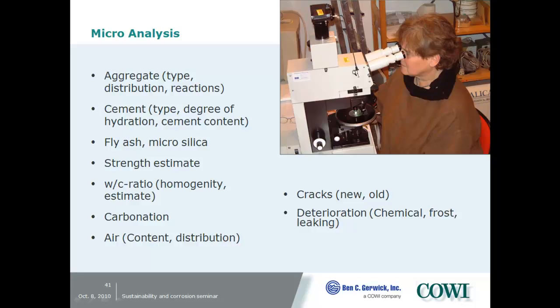Strength estimate, as said. Water cement ratio we can also estimate to a fairly good accuracy. You need to have some references, and what you evaluate is the porosity. If you have a very light green color on your cement paste, that's a high water cement ratio, and vice versa. So you need references to do so. Trained petrographers can evaluate with an accuracy between 0.02 and 0.05 in water cement ratio, which is actually very good.